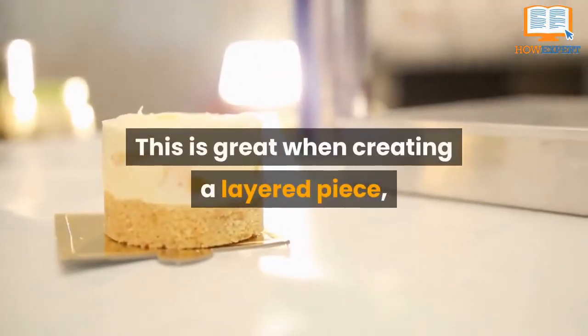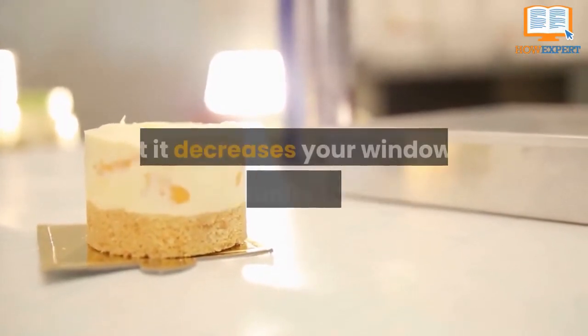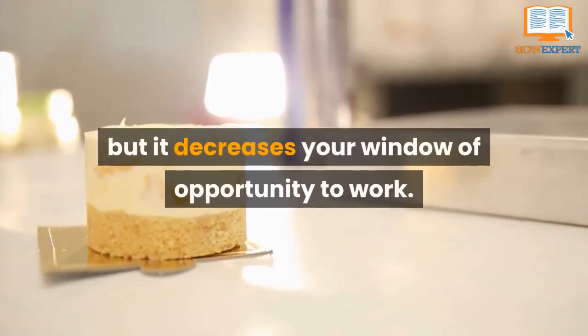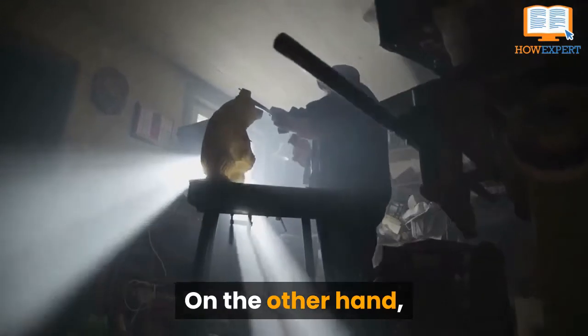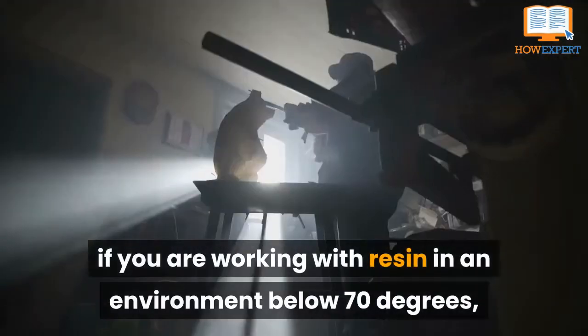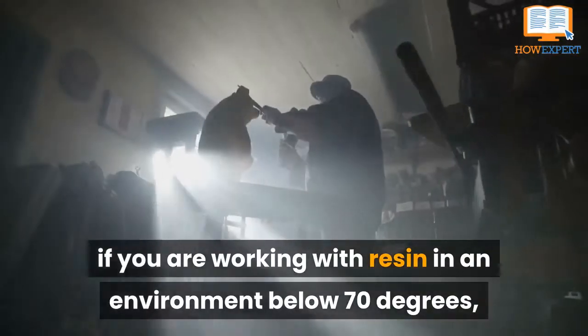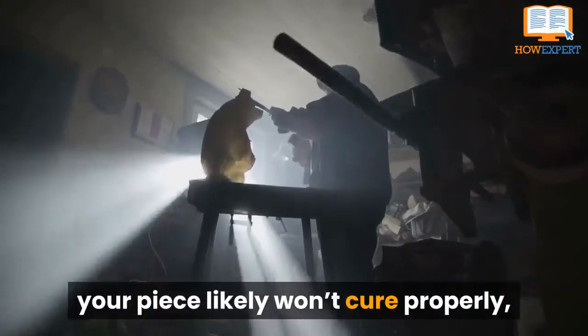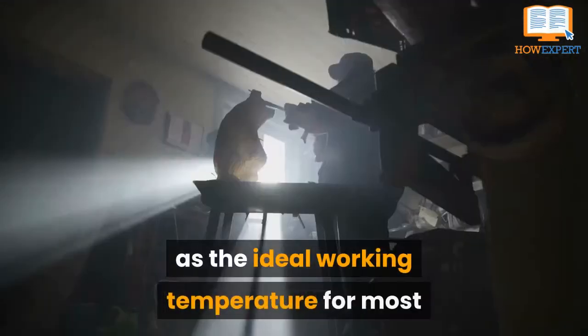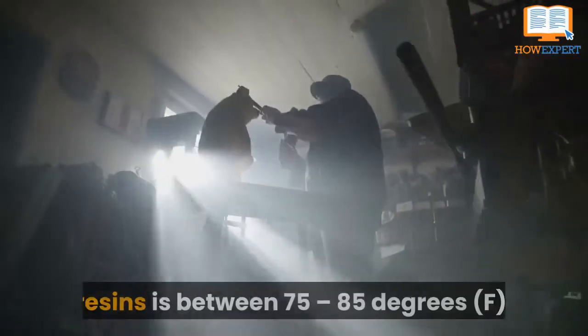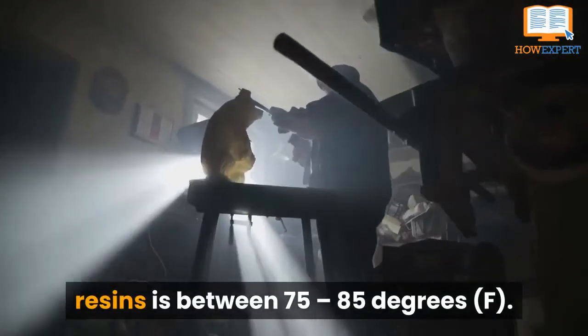This is great when creating a layered piece, but it decreases your window of opportunity to work. On the other hand, if you're working with resin in an environment below 70 degrees, your piece probably won't cure properly, as the ideal working temperature for most resins is between 75 and 85 degrees Fahrenheit.